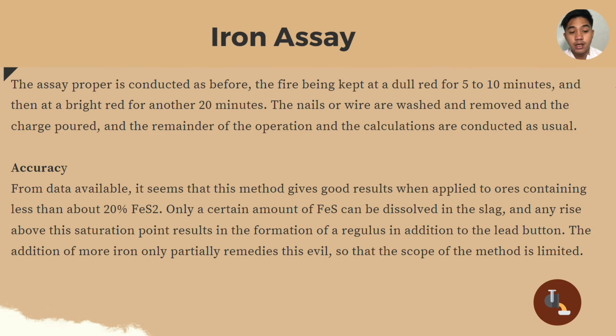Accuracy. From the data available, it seems that this method gives good results when applied to ores containing less than about 20% of FeS2. Only a certain amount of iron sulfide can be dissolved in the slag, and any rise above this saturation point results in the formation of a regulus in addition to the lead button. The addition of more iron only partially remedies this evil, so that the scope of the method is limited.